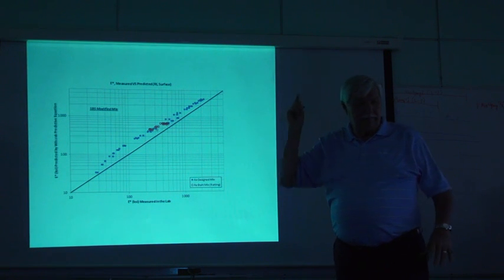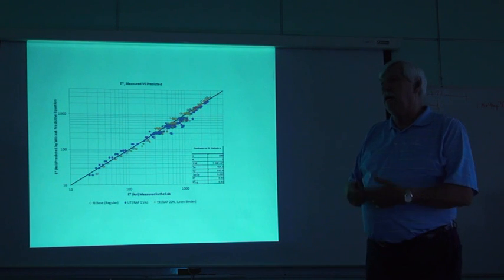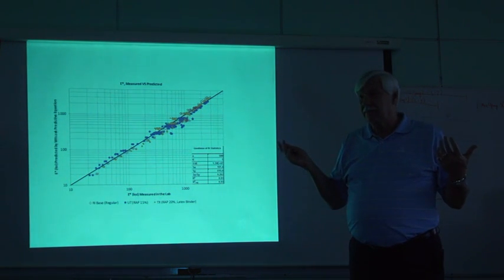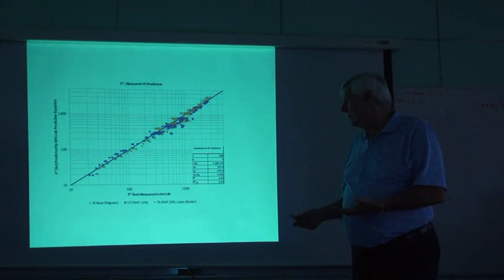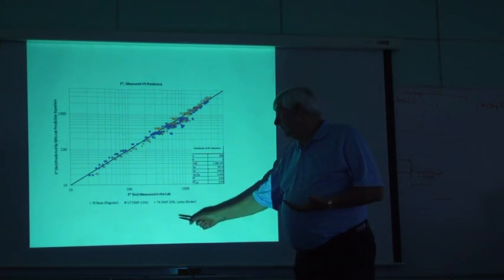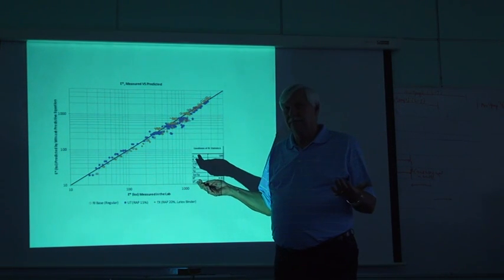But you see, for the one surface mix, which was SBS modified, it is off. But when I look at all the other mixes that were used, the Rhode Island based, the non-modified mixes, and look at the measured values against the Witczak predictive equation, they're right there.